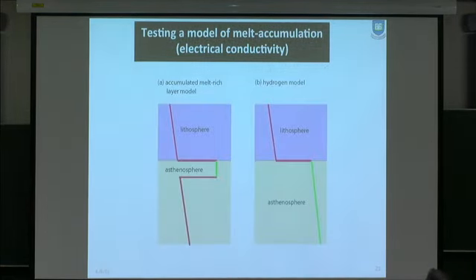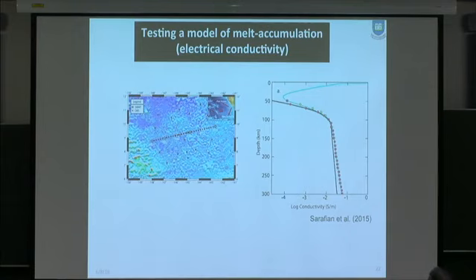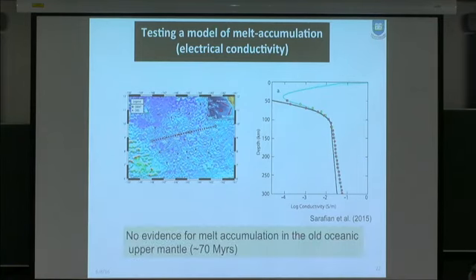How about the electrical conductivity? If you have a melt accumulation, you expect a peak in the conductivity. But if the hydrogen mechanism is correct, you expect something like this profile. So there was a project. This is the no-melt project, like an anti-melt project. They went to a typical 70 million year old Pacific, and they found a pretty smooth profile of conductivity based on a very dense array. Okay, and this is in a way not consistent with the idea of melt accumulation at the lithosphere-asthenosphere boundary, at least in this region.